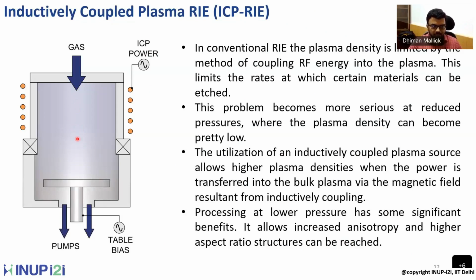The combined effect of decoupling the plasma creation and directionalizing the ions is that you can increase the anisotropy. You can understand that because now you have a very high plasma density, so more ions are created, and they are highly directionalized because you have a different mechanism for directing those ions towards the substrate. So you get a lot of anisotropy, and because of this high anisotropy, you can create high aspect ratio structures onto the wafer using this inductively coupled plasma RIE technique.